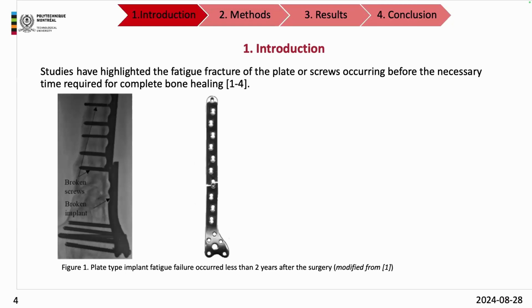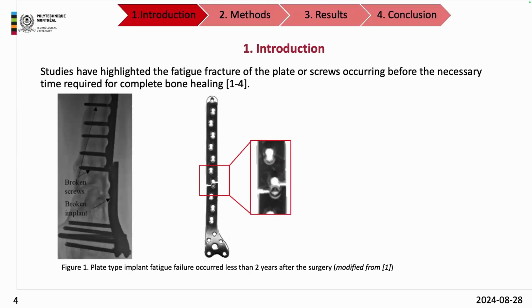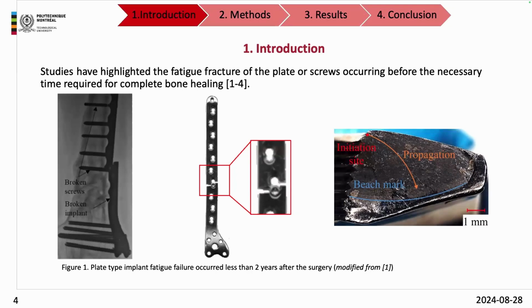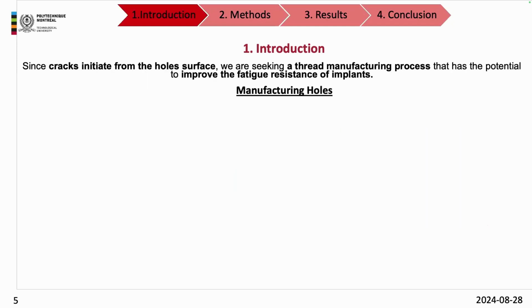Actually, if we go into the detail of the fracture of this implant, we found that the fractures always occurred from the vicinity of the hole. And if we look at the fracture surfaces, we found the typical fracture surfaces of fatigue failures initiated from the top of the holes. Now, since we know that a crack initiated from the hole, we are seeking a manufacturing process to improve the fatigue resistance of this region of the implants.